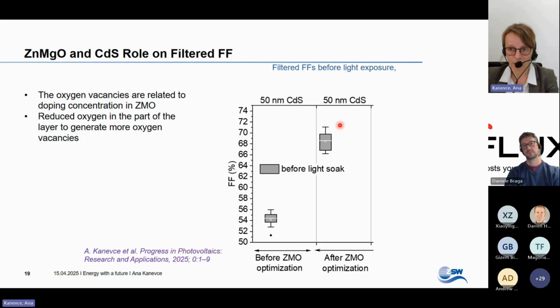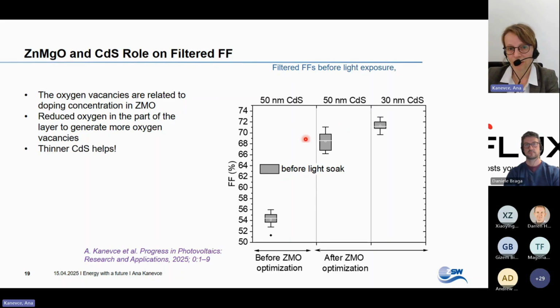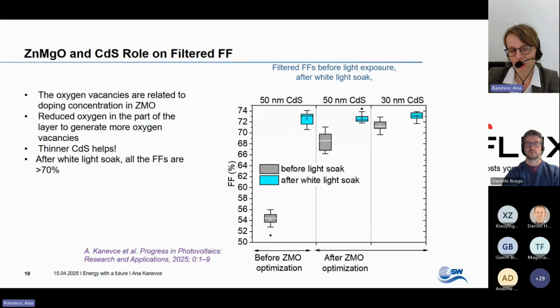Now the question is, does cadmium sulfide help? Can we still thin the cadmium sulfide? The answer is yes. Decreasing the thickness of cadmium sulfide from 50 to 30 nanometers improved the fill factor. Now, we light soak those cells. After the light soaking, all of them were the same. So if we measured everything with light soaking before, we would just have been blinded by the light, and we wouldn't see which cell has a problem and which one does not.